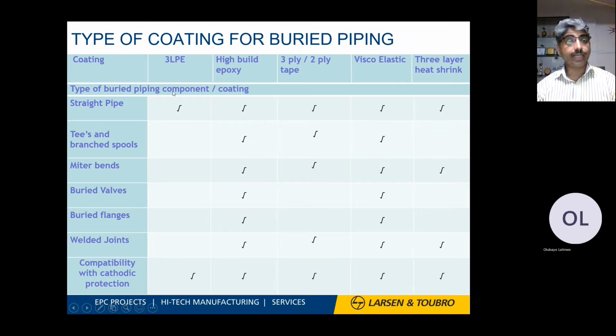Now coming to the selections, typical coating for buried applications, what is for what? You have a straight pipe, you can use all the types which we discussed. If you have a T-bend, or if you have weld joints or buried miter bends, there is a restriction to only 3 processes, that is epoxy coating, 3-ply and viscotape, because this is a field application requirement. So these are the field applications. 3-layer heat shrink again is a field application. So all these things we have to do at field. So there is only this limitation. Only straight pipe and